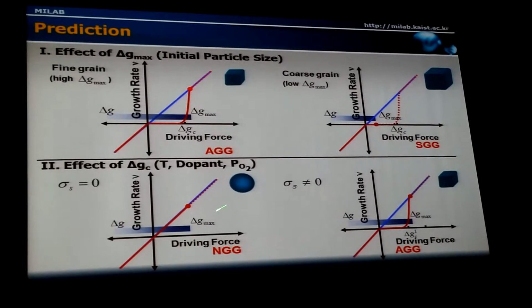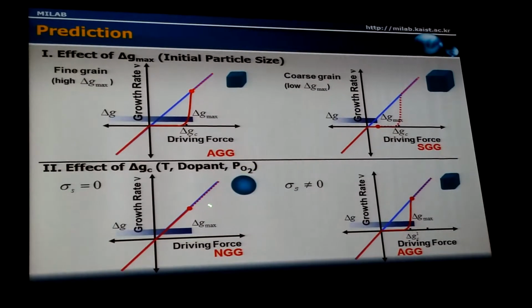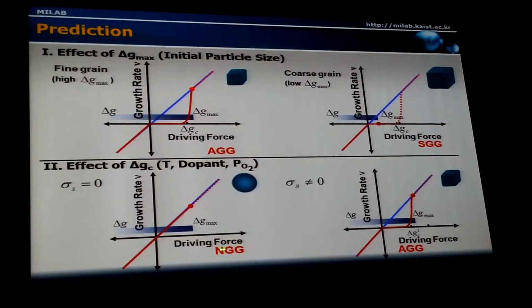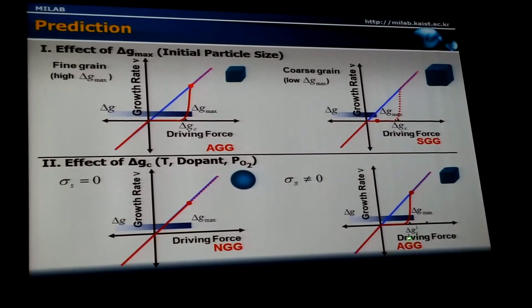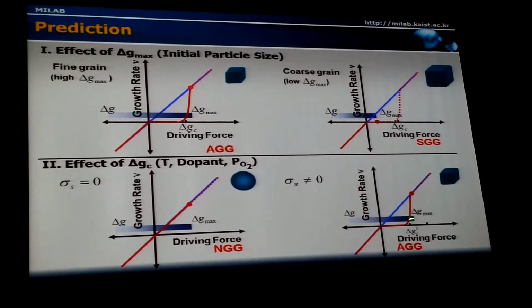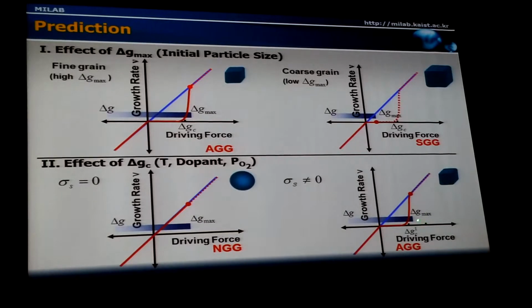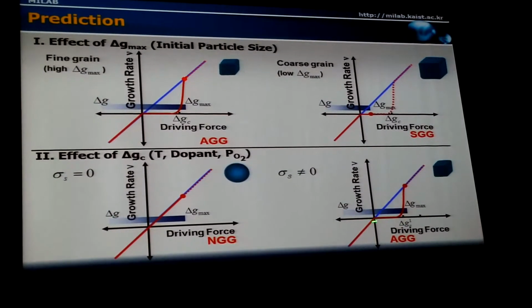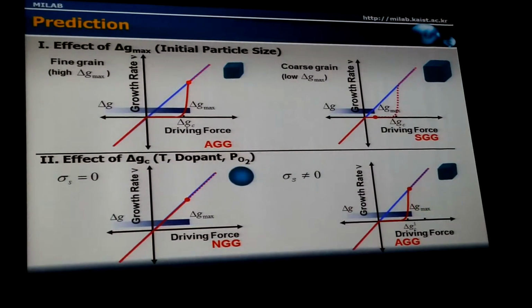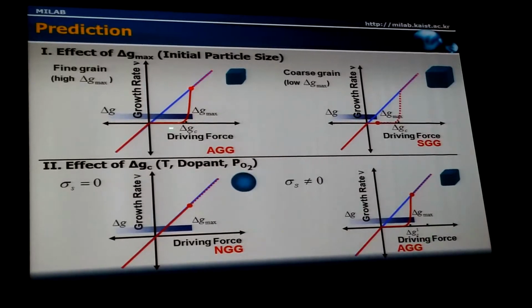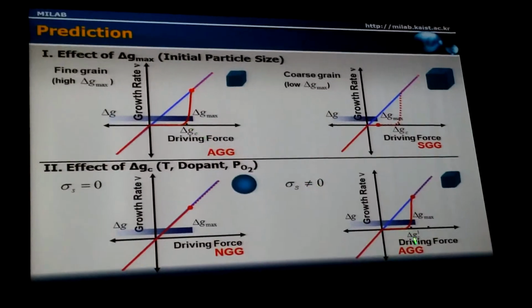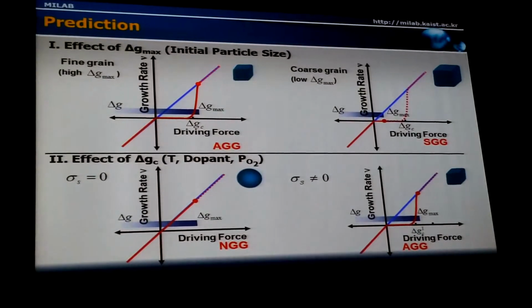In the case of the rounded, disordered grain boundary, normal grain growth is predicted, but in the case of faceted grain boundaries, the maximum driving force can be larger than the critical value. A critical driving force comparable with the maximum driving force means that abnormal grain growth will occur.